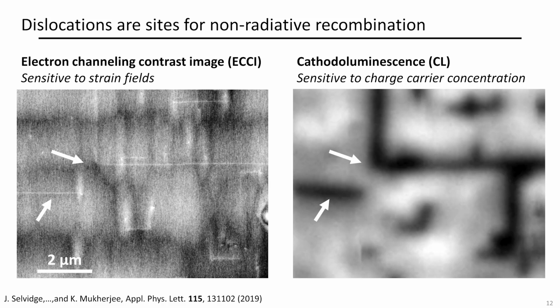This image in one slide illustrates part one of why dislocations are bad. So on the left, you're seeing a strain-sensitive map. Maybe many of you might remember that dislocations have strain fields. Right? So you can actually use a nice electron microscopy technique, not even TEM. You can use SEMs today to actually look at the strain field from a dislocation. So that's the image on the left. The image on the right is the light emission map from that same region. And everywhere you see a dislocation on the left, you see darkness on the right. Right? So in a nutshell, this is why dislocations are bad. Because if you want to make a light-emitting material, you don't want to see darkness.